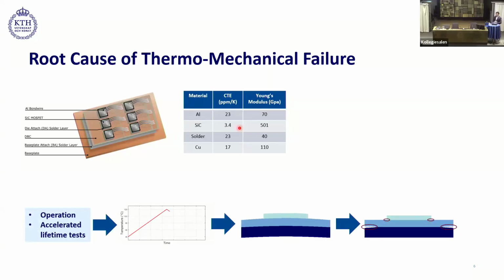So during operation, the temperature inside the device is cycled because of the power losses, which eventually results in thermal expansion and contraction of these materials. Since they have different coefficients of thermal expansion, these materials will expand and contract at different rates. This eventually results in interfacial fatigue, which generates cracks. And because of the cracks, delamination occurs, which eventually results in the semiconductor device failure.